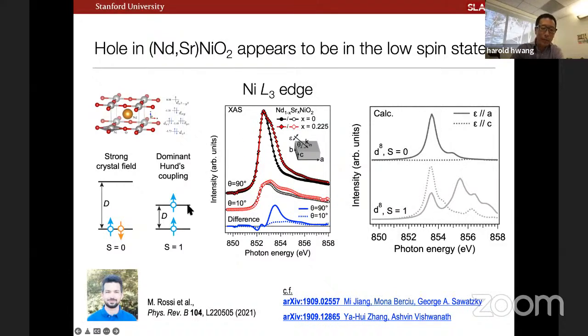And just to illustrate what I'm talking about here, the question is, if I just take these top two levels, if we remove an electron, where does it come from, right? And so you may think that we take the topmost electron. That's what we seem to find. That's in a regime where the crystal field splitting is the largest energy scale of the problem relevant for this question. But of course, you are very close to being in a regime dominated by Hund's coupling, right? That you'd rather take this lower electron out in order to maintain Hund's energy. And so if we look at, say, a doped versus undoped nickelate in nickel L-edge XAS, we can conclude that we are predominantly in the low spin hole-doped state.